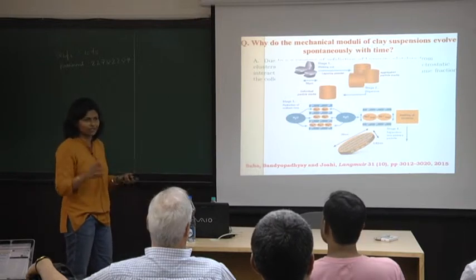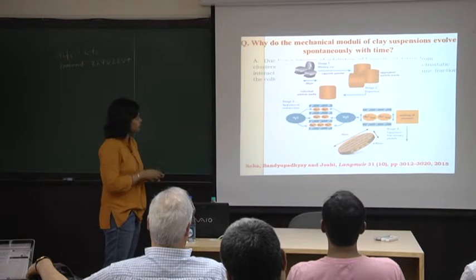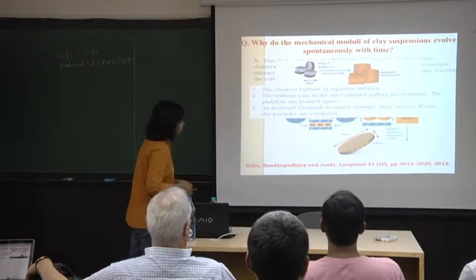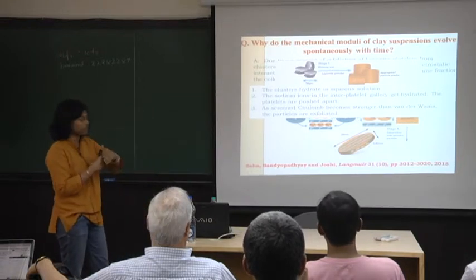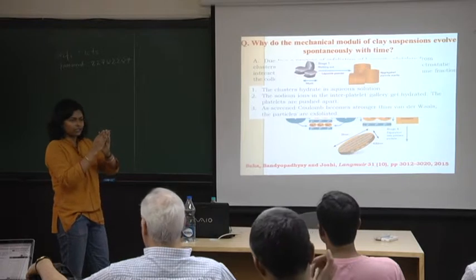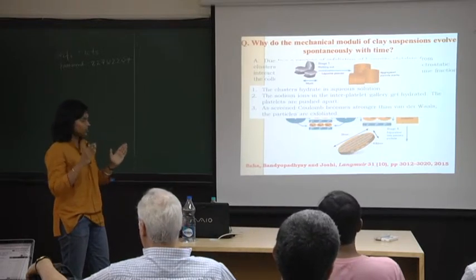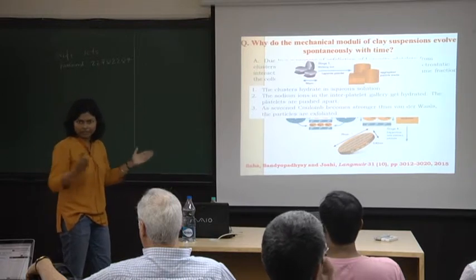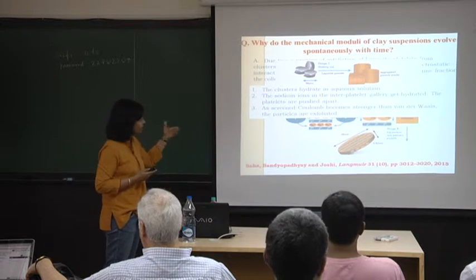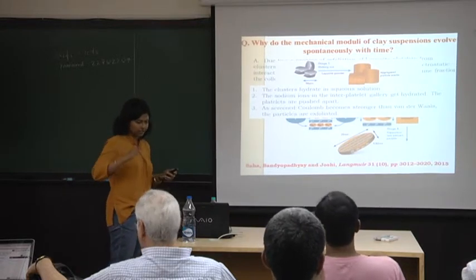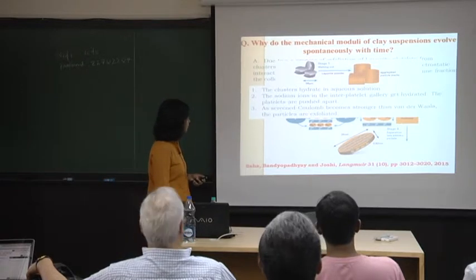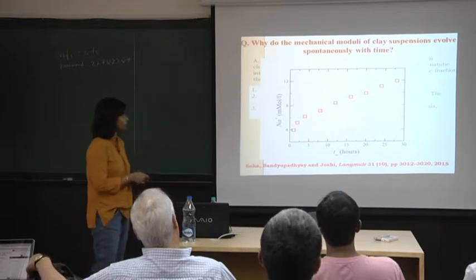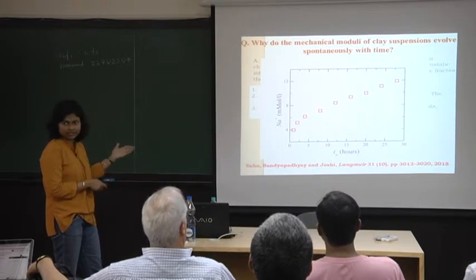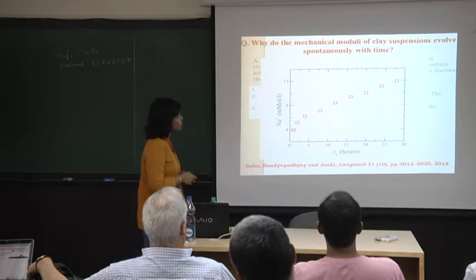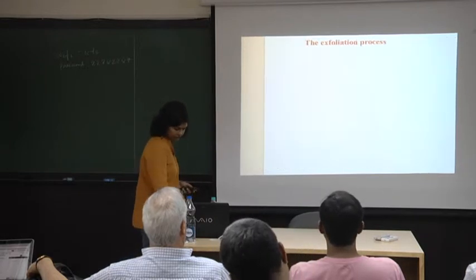Swelling of clay is something that industrial chemists do a lot of. It's a very important property. So the clay basically swells, and you have an attractive van der Waals interaction between the particles. When the clay stack has swollen enough that the van der Waals interaction is exceeded by the screened repulsion, you have particles that just come out of the stacks one by one. Okay. So we have measured the sodium ion concentration in solution, I'll come back to this later, and it does evolve versus TW, which is the aging time in this case, the time since preparation of the sample. So once again, it's a spontaneous process.